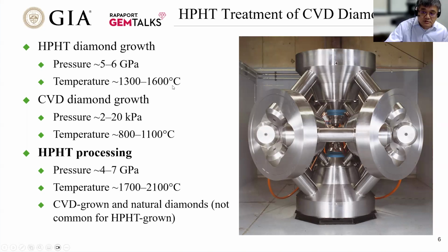So this is the growth of diamond, and CVD grows at a much lower pressure and lower temperature, as we mentioned. When we treat a CVD grown diamond with a brown color, the pressure is about 4 to 7 GPa. We still need a press like this to generate the pressure to avoid the CVD diamond getting graphitized at a temperature from 1700 to 2100 degrees C. This is a very, very high temperature. So we need pressure to avoid the graphitization of the CVD diamond. That is similar to the treatment of natural brown diamonds at high pressure and high temperature to remove the brown color from the natural diamond.